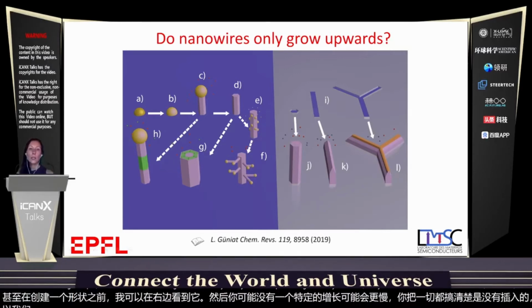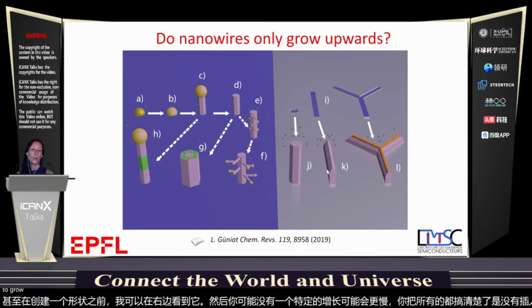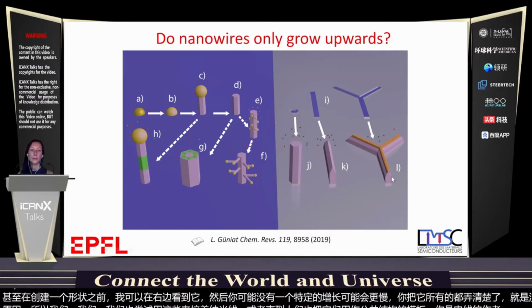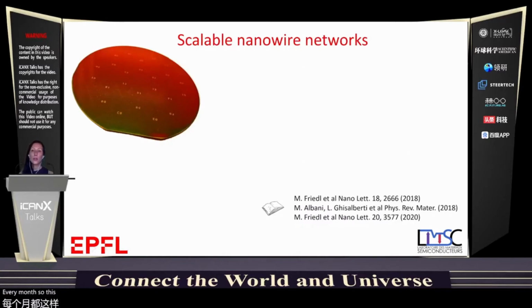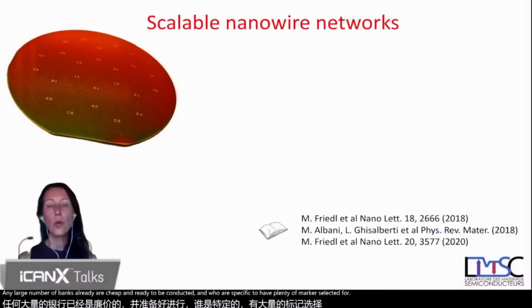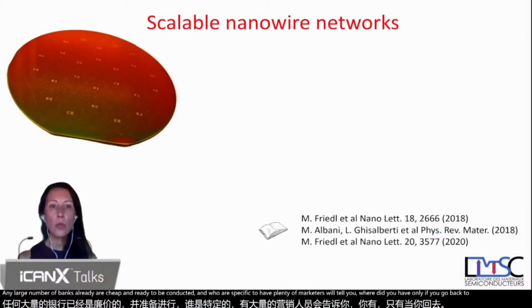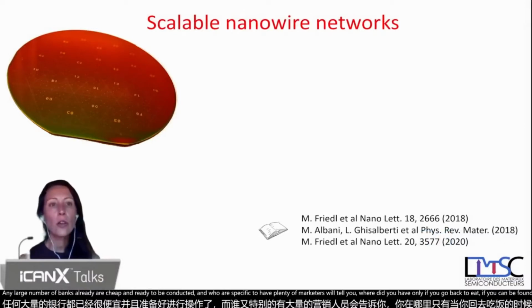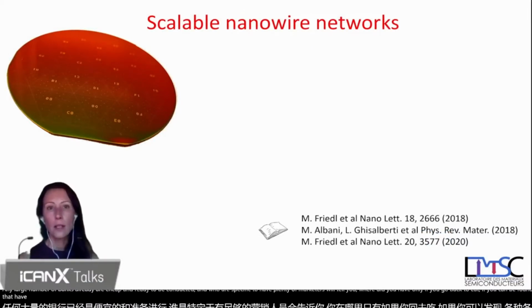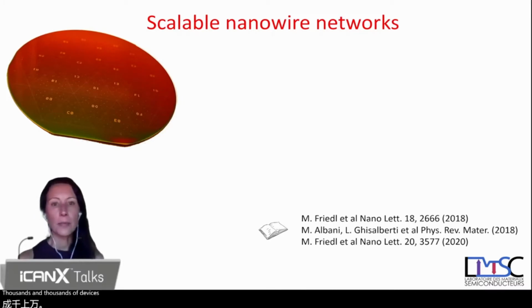So we tried this also to grow the nanowires horizontally, but also to use them as templates for more complex structures, to have even other nanowires going on top. So this is for us a way to obtain scalable nanowire networks in which you grow a very large number of nanowires already on chip and ready to be contacted. And as you see here, you have plenty of markers so that once you have grown, if you go back to the e-beam, you can define all kinds of electrical contacts to make your devices, and you have thousands and thousands of devices on chip.